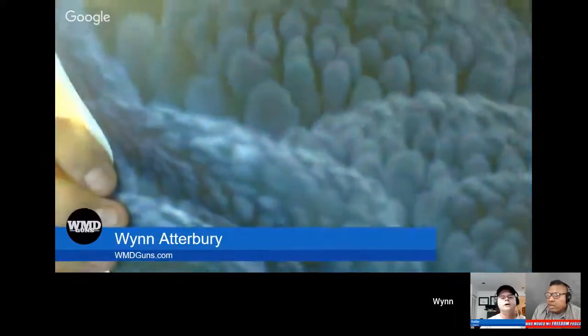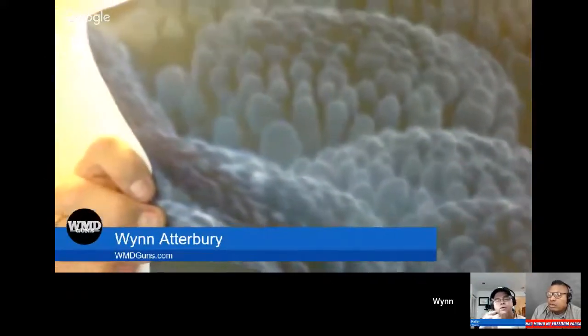So if you picture the coating growing up, like this is the substrate, your hand is a substrate, and it grows up in columns like your finger. Then you put your fingers together and it looks like a broccoli field, right? So you can see all the surface area that's been created. And if you zoom up on that broccoli field, on a microscopic level, that's what it looks like? It looks like this. So it's almost like a radiator, like cooling fins on your electronic device. Wow. So you've increased the surface area by about four times.